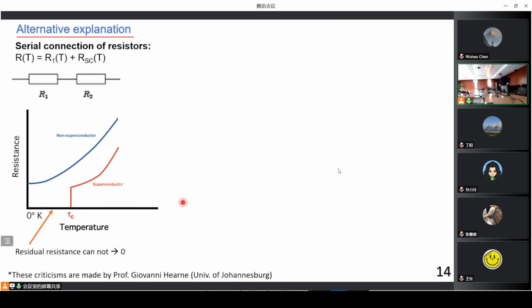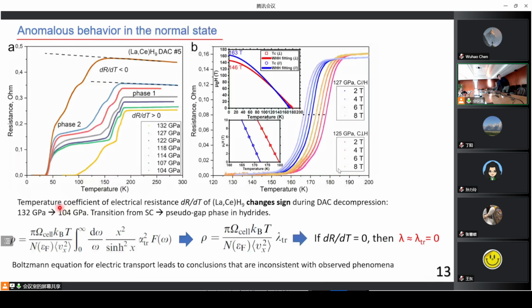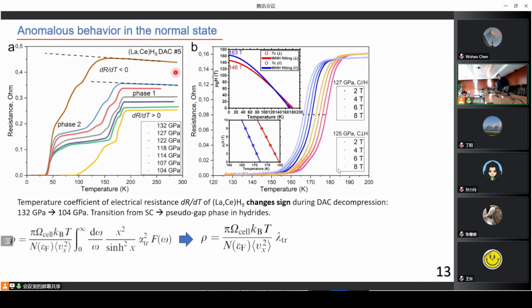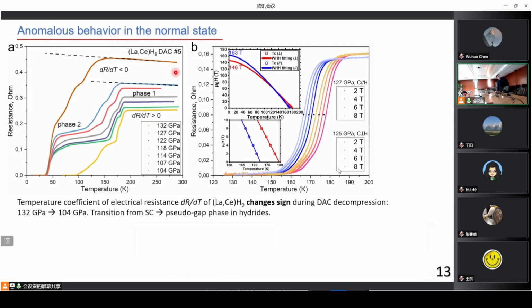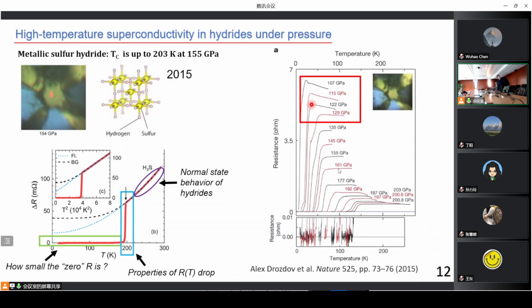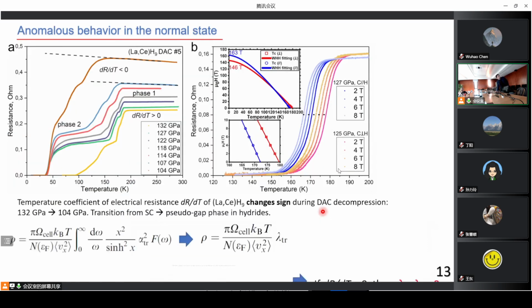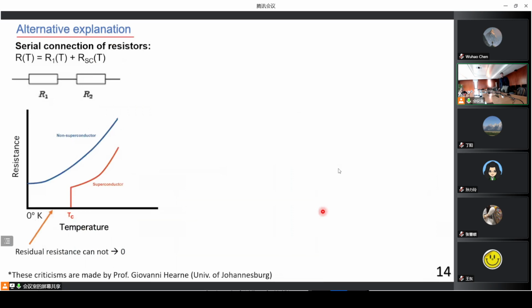Maybe something happened with the sample, maybe several phases appeared, maybe a phase transition. Okay, if we connect two resistors together, one resistor being this superconducting sample, the second resistor will give us residual resistance after the superconducting transition, but there is no residual resistance in both cases. In the case of lanthanum-cerium hydrides, and the same for superhydrides, there is no residual resistance, so it's not a serial connection of resistance.